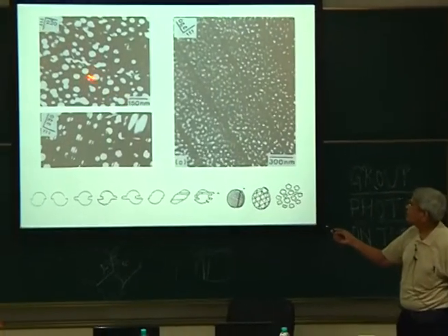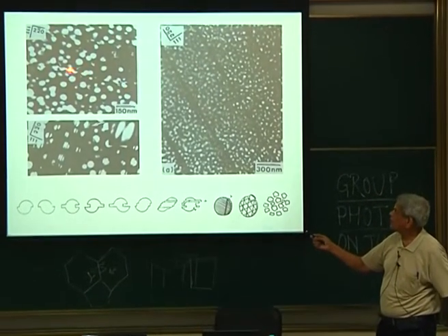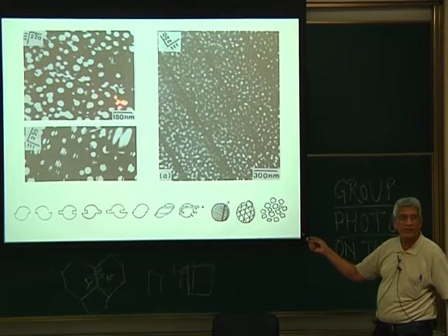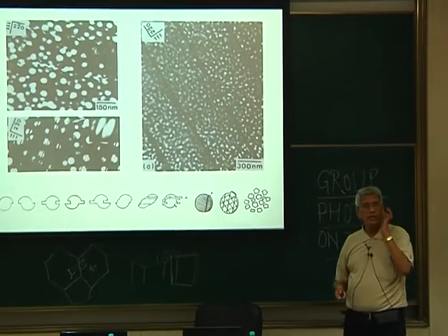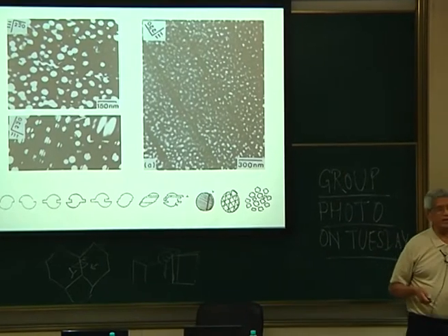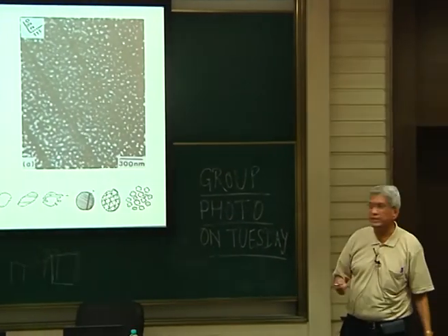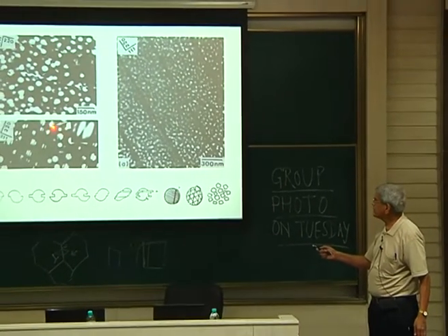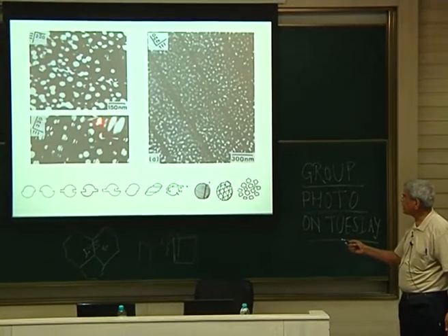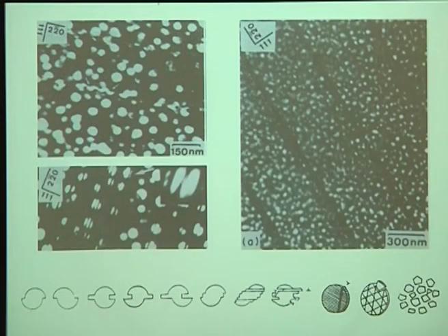Here you can see these particles which are sliced into half, correct? In this particular one, if you see it, this is a microstructure where the number of cycles has been increased. Other than the particles which have been sliced in this direction, in the cross-slip direction also, the particles are getting sheared.